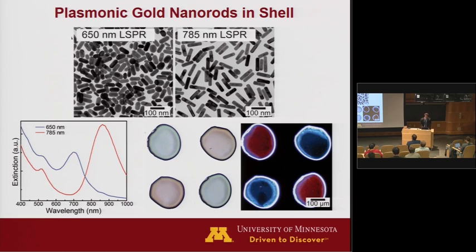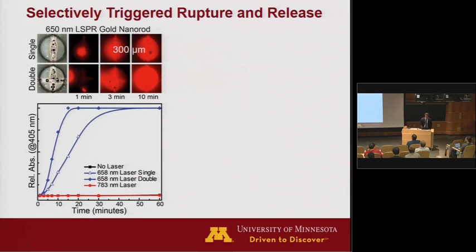Same thing here. So the question is, does this actually work? And it turns out, surprisingly, that it does. So this is a capsule that we printed, a core shell capsule. You have your core, you have your PLG shell. Within that shell are these shorter rods. And then we trigger it with a laser that we also connect onto a 3D printer so it can raster scan the rods into the matrix. And you can raster scan it over the capsule.